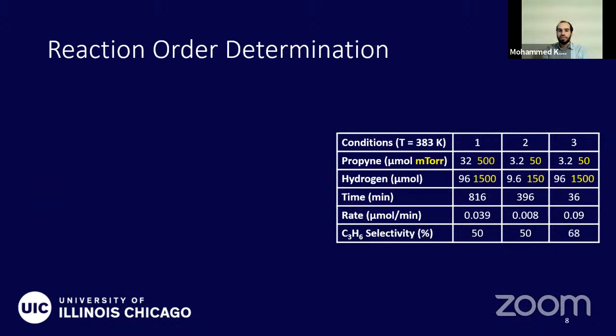So the next step was to carry this out under different conditions to try to determine the reaction order. And so using these three conditions, here I've labeled the reactant amounts in micromoles as well as millitorr. Since these are gas phase reactions, we use partial pressures. And so from here, we can determine the rate law, which comes out to this equation. So approximately 1 for the rate order with respect to hydrogen and negative 0.36 with respect to propyne.